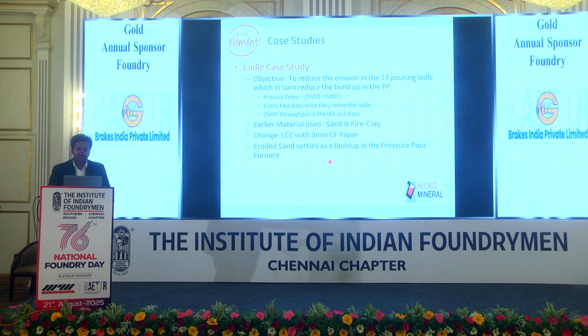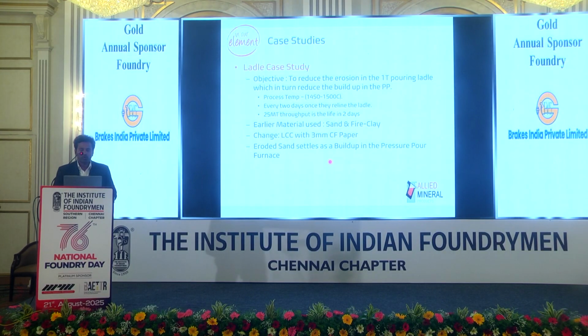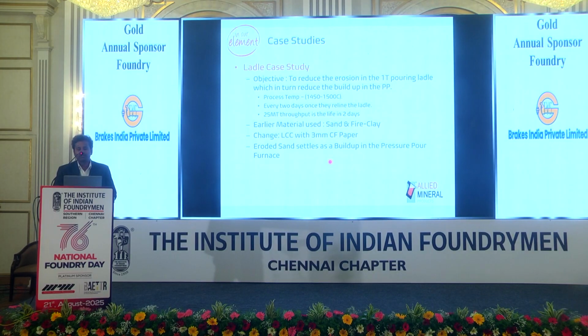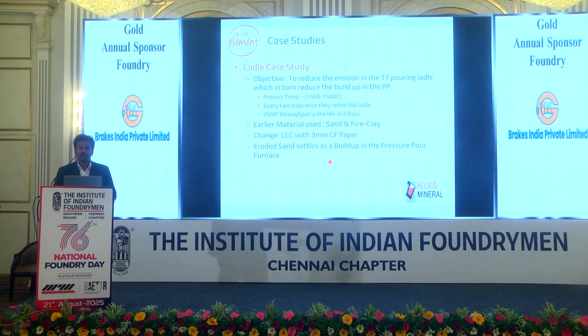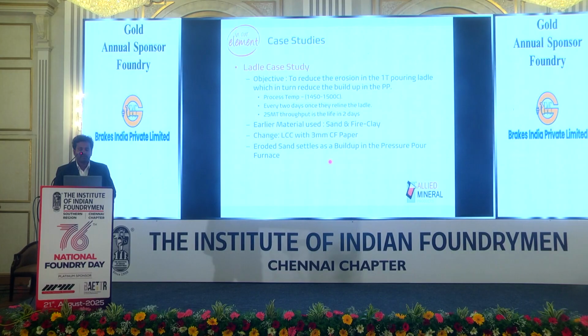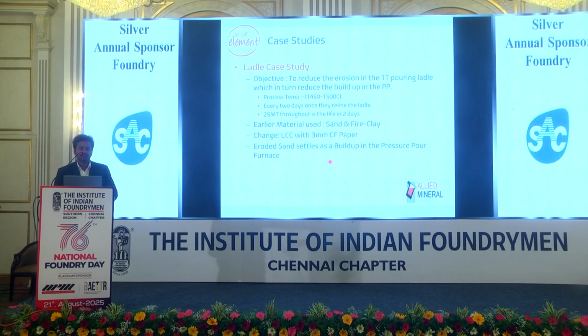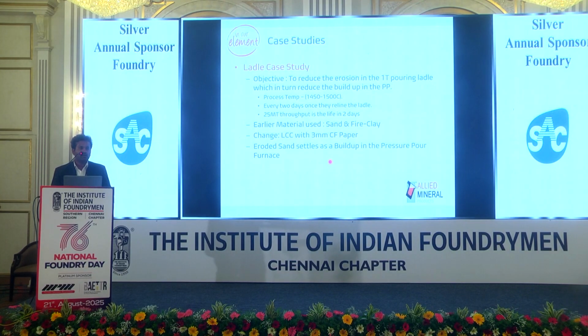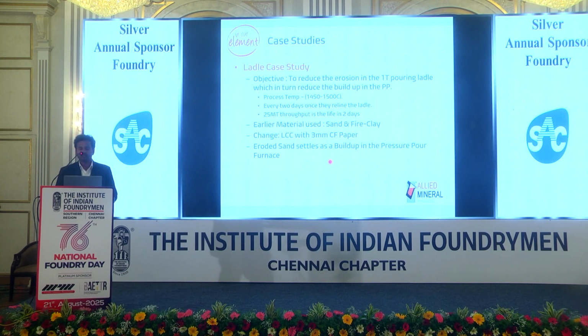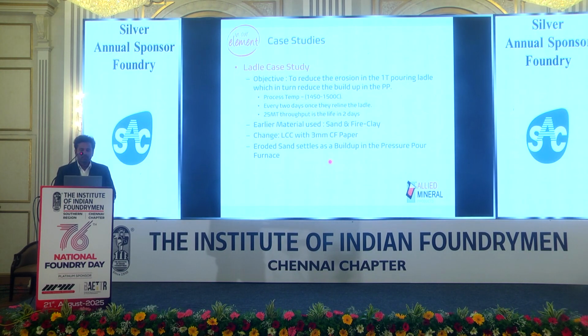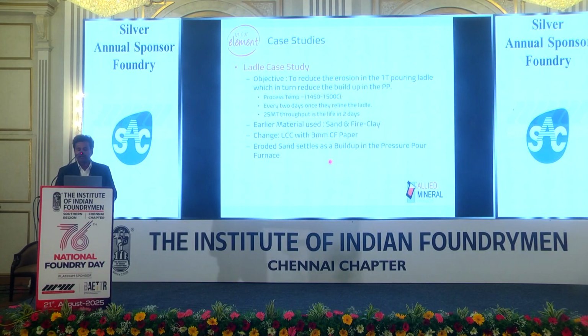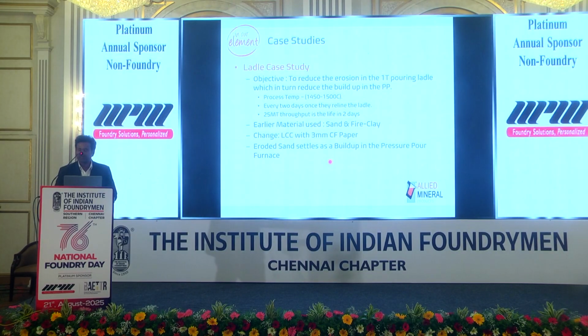And this case study is for a pouring ladle, to reduce the erosion in a 1T pouring ladle, which in turn reduces the buildup in the pressure pour. The processing temperature is 1450 to 1500 degrees Celsius. The life of their existing ladle is only 2 days, which is 25 metric ton. Earlier they used to use sand and fire clay, and we changed it to low cement castable with ceramic paper.